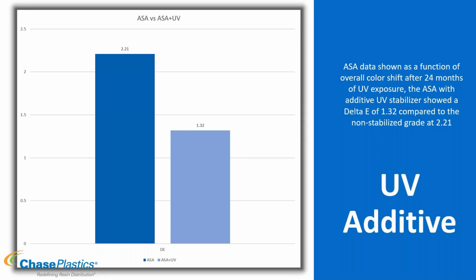If you want less color shift after UV exposure, you want a lower delta E value. In this case, your ASA with no UV additive tested at 2.21 delta E. Your ASA with UV additive tested at 1.32. So it did not change its color as dramatically as the one without the UV additive. All this to say, I added a UV stabilizer, exposed it to UV, and the material with the stabilizer held onto its color better than the grade without it.